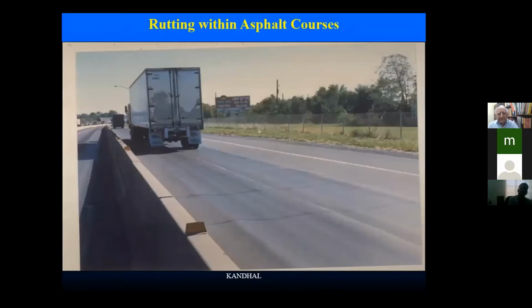Now, this is a picture on a national highway in the US, and you can see a lot of rutting in here. But since the rutting here is very, very smooth, you can see there's a flow of the mix on the side, a hump is there, but very smooth. So I would suspect that this rutting is being caused in the bituminous layer and not due to subgrade.